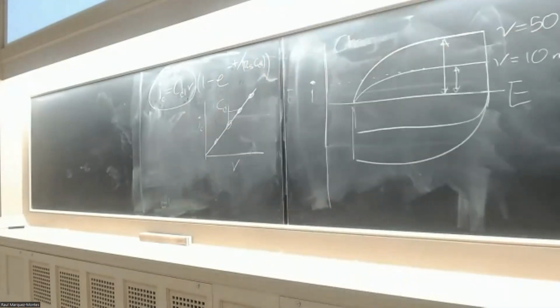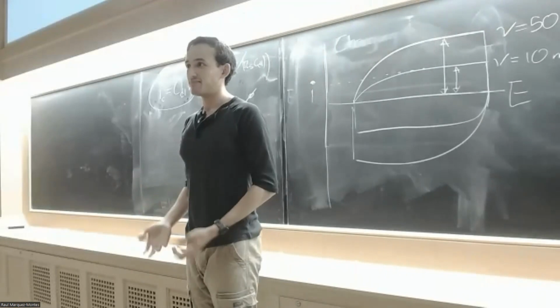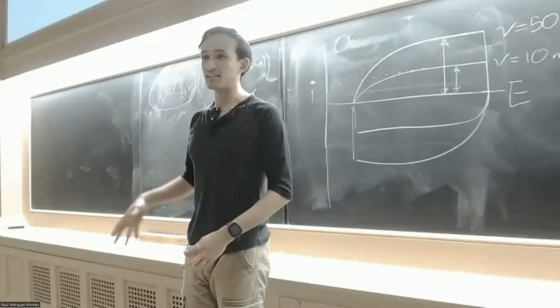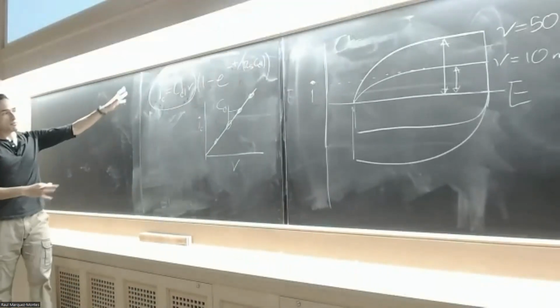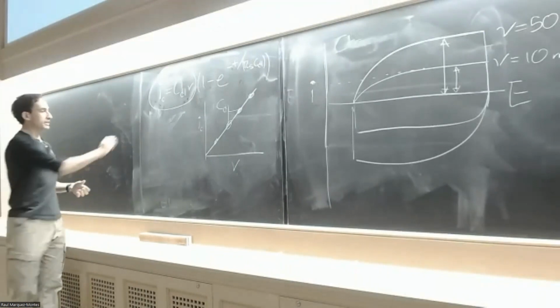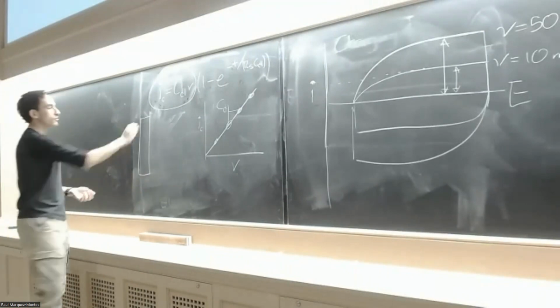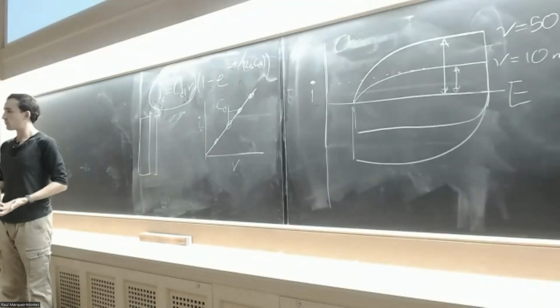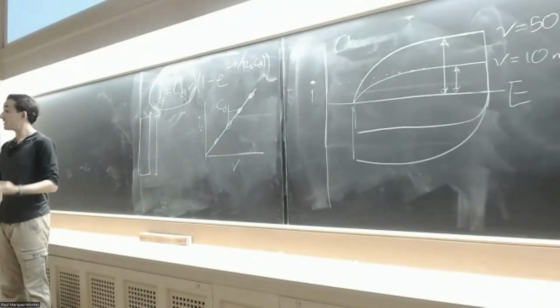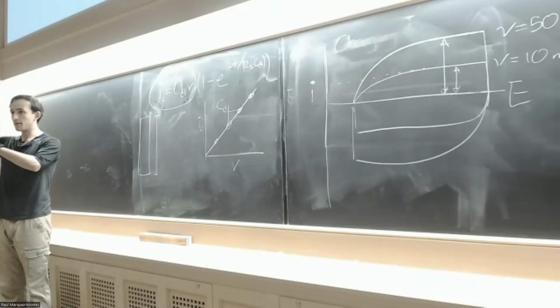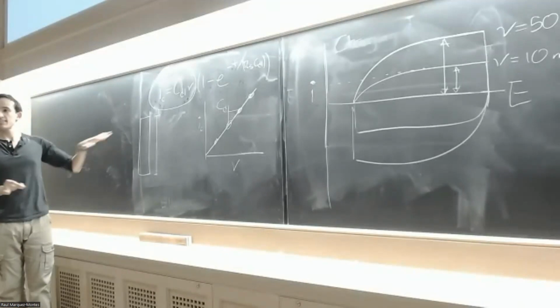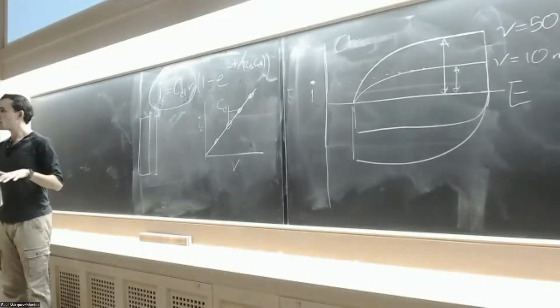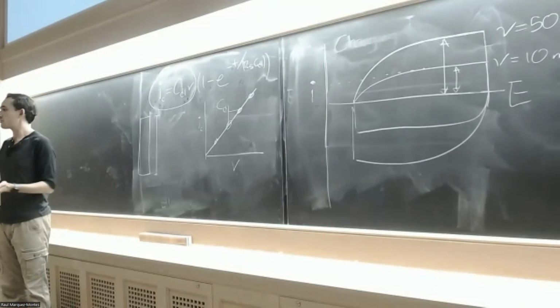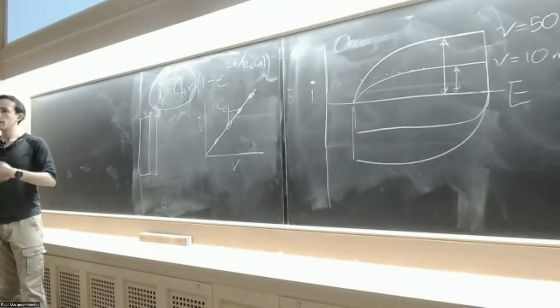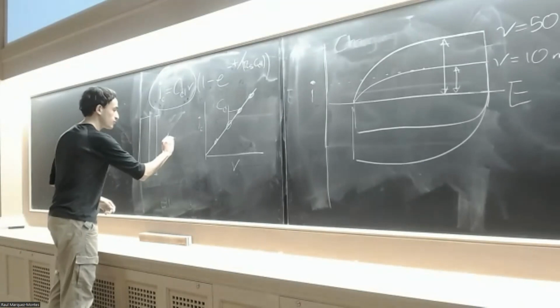And just a final remark before I give you some experimental evidence: maybe you're wondering, having just talked about double layer capacitance, where's the area? We need to use the area, and you don't see any square centimeter units here. Well, remember that this is for measuring the double layer capacitance of an electrode surface. So let's say that we have an electrode, and we know the area beforehand, using a powerful technique like BET or AFM, atomic force microscopy. With AFM, we can map the surface and know precisely the surface area. So let's say we have a very beautiful electrode, shiny, smooth, and perfect platinum, nickel, whatever conductive material you want, and we know by using AFM, BET, or any other technique that the surface area here is 1 square centimeter.